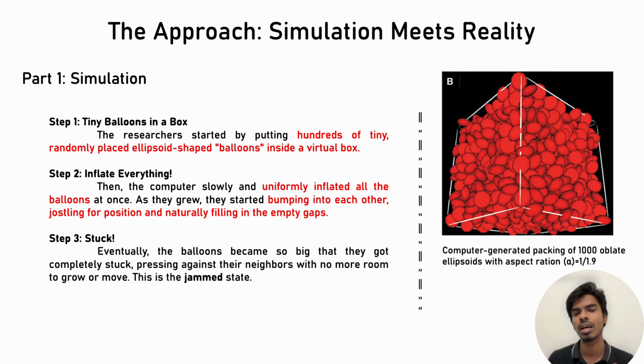The authors were interested in simulating the random packings here. For that, they used an algorithm to simulate all those random packing movements. What they did is start every one of those particles as small point particles, and then try to inflate them with vibrations. As the particles grow in size, and also have vibration, they settle into some most favorable, or less entropic, arrangement. Okay, so that's how the simulation works.